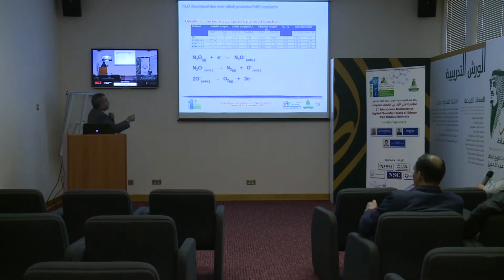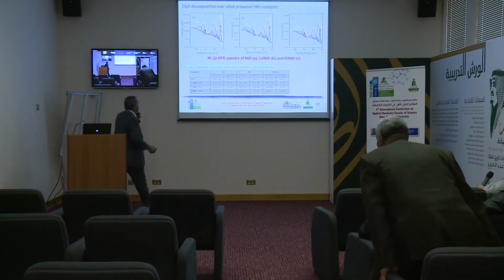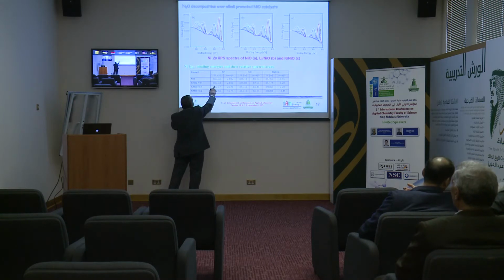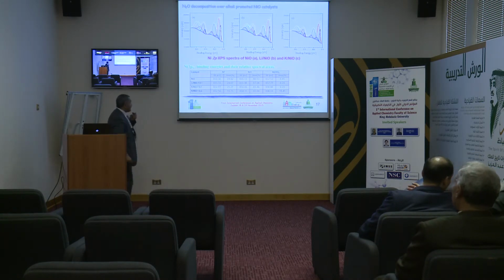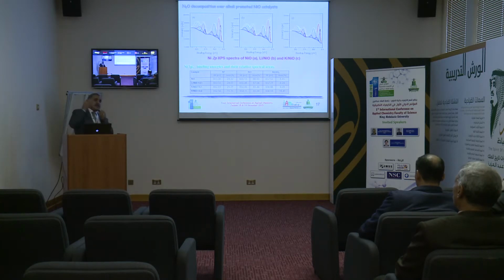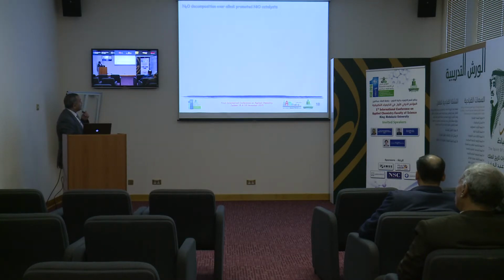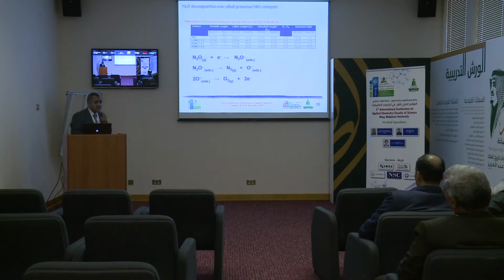So, let us recall the nickel metal here. Upon adding potassium or lithium, one can observe a noticeable decrease in the binding energy. This means the nickel metal in this state has more ability to give electrons. That's why the first equation is facilitated in the presence of the added alkali cations.